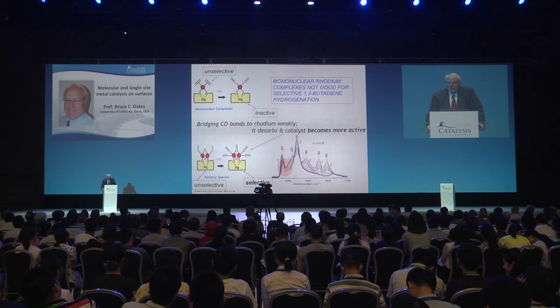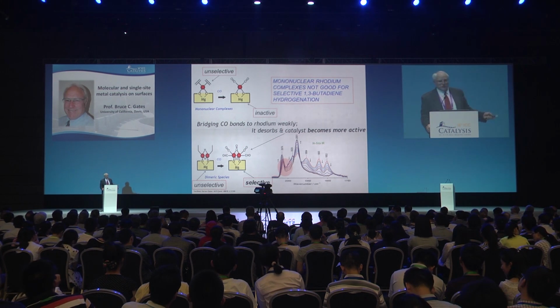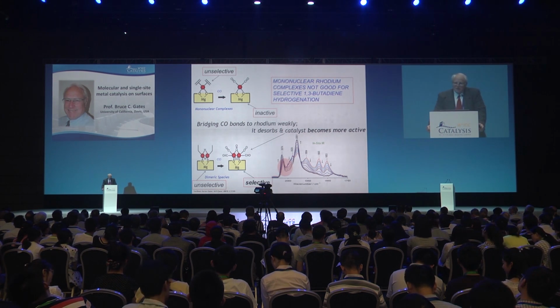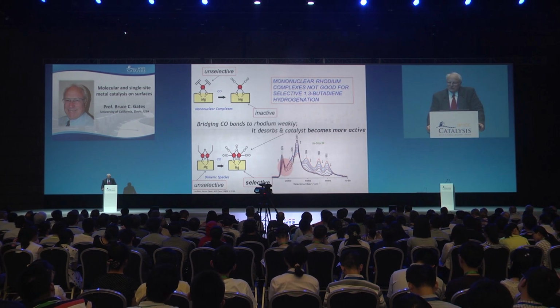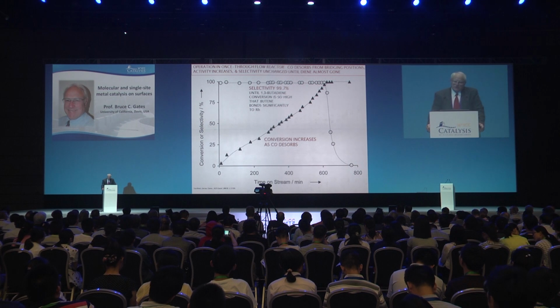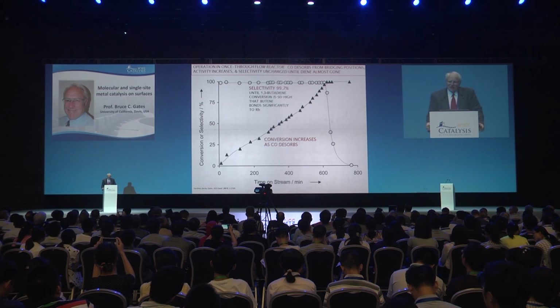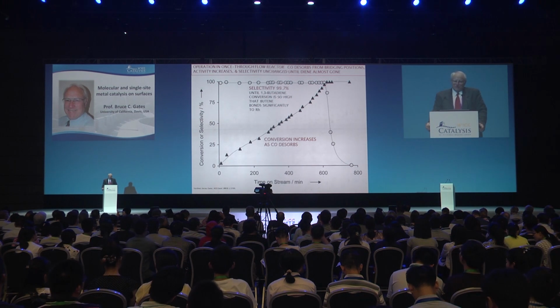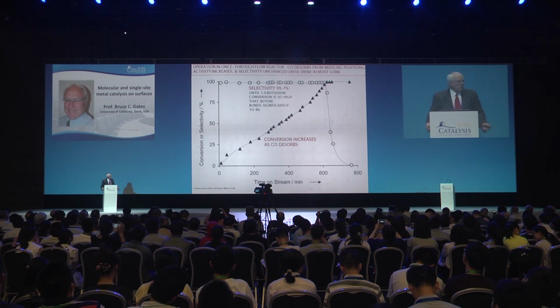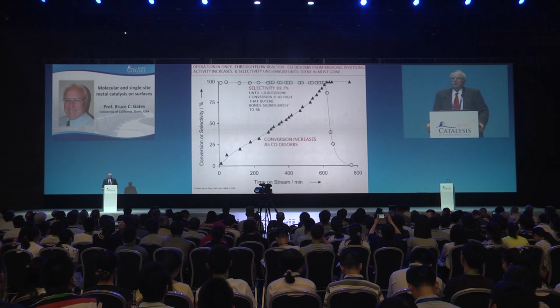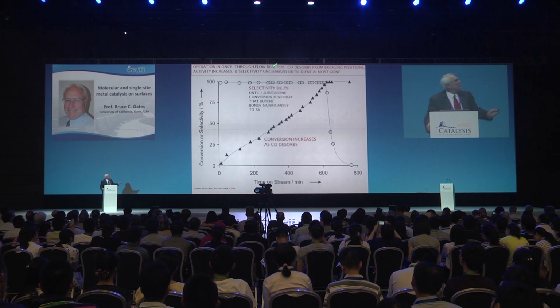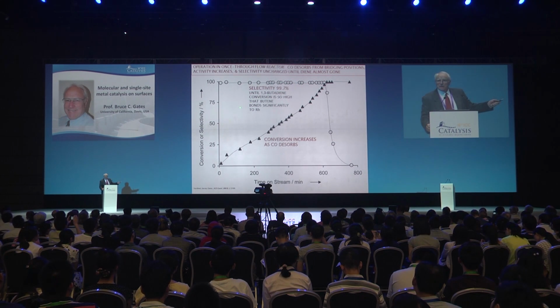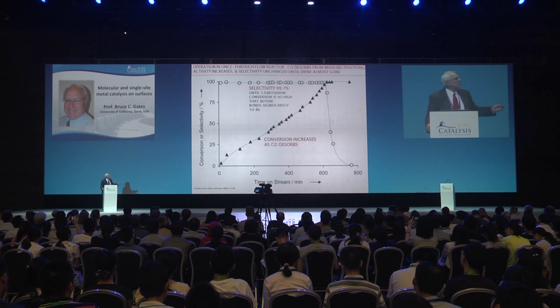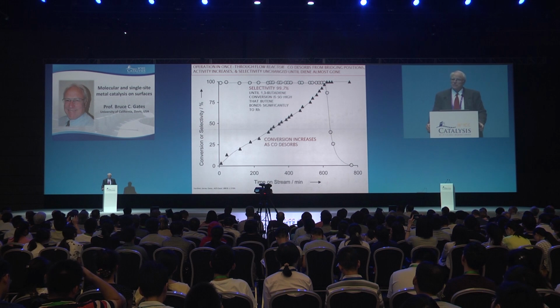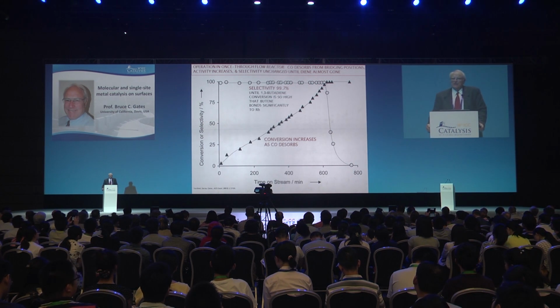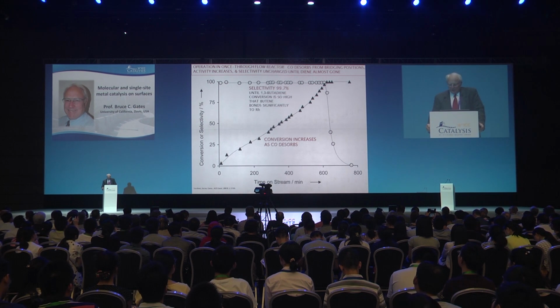What goes on with that catalyst is it has bridging carbonyl ligands. They show up in the infrared, and they're relatively easily removed during catalysis. So we start with a catalyst that's low in activity because the carbonyl ligands are populating the rhodium centers in the dimeric structure. But over time of operation, the bridging CO leaves, the activity goes up, and the selectivity holds—extremely high selectivity with this catalyst—until conversion is so high there's hardly any butadiene left, and then the butene starts bonding to the rhodium, giving butane formation in an unselective catalyst.